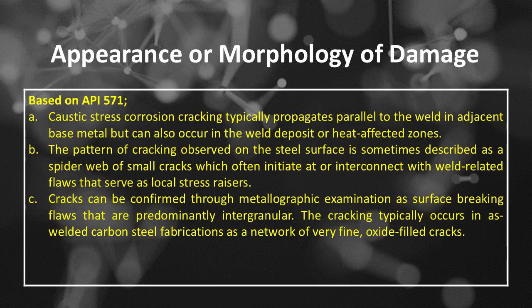Number B. The pattern of cracking observed on the steel surface is sometimes described as a spider web of small cracks which often initiate at or interconnect with weld-related flaws that serve as local stress raisers. Number C. Cracks can be confirmed through metallographic examination as surface-breaking flaws that are predominantly intergranular. The cracking typically occurs in as-welded carbon steel fabrications as a network of very fine, oxide-filled cracks.